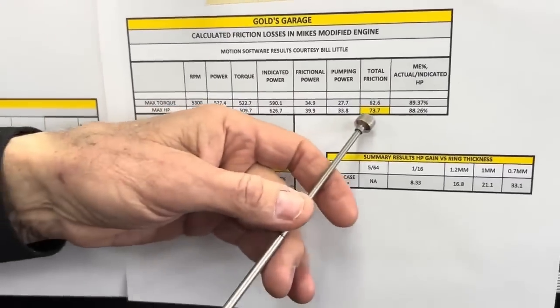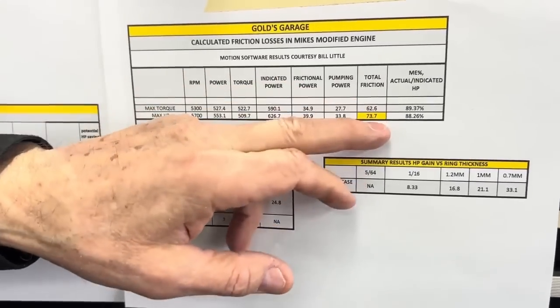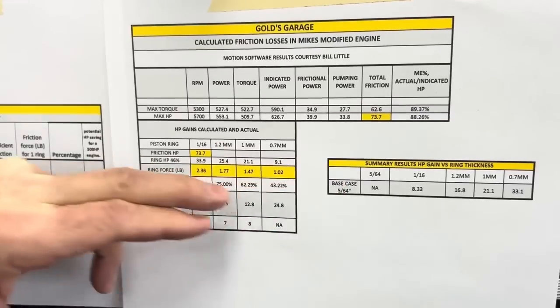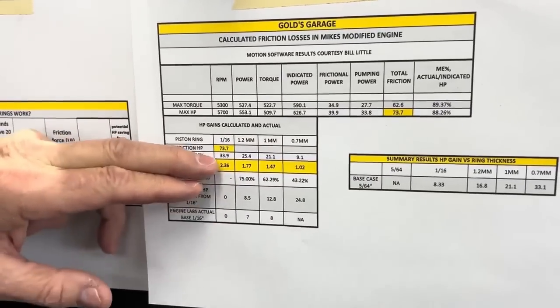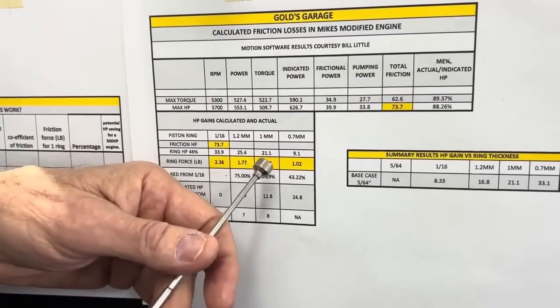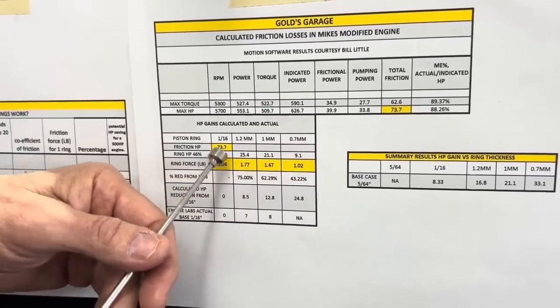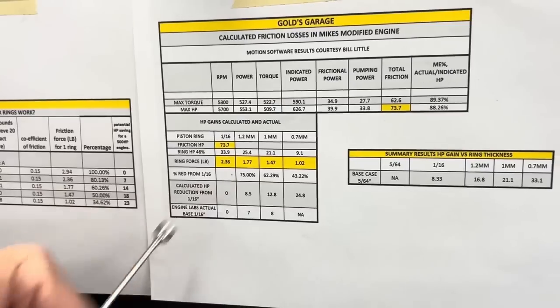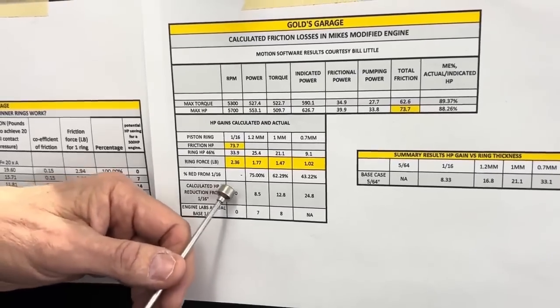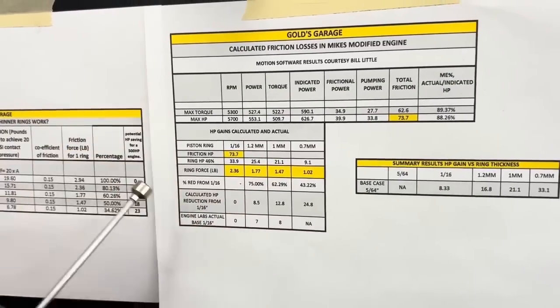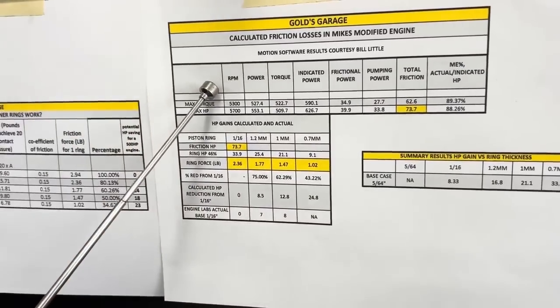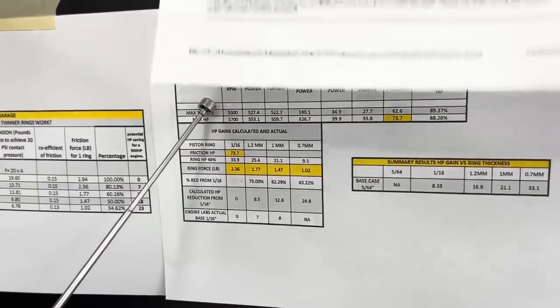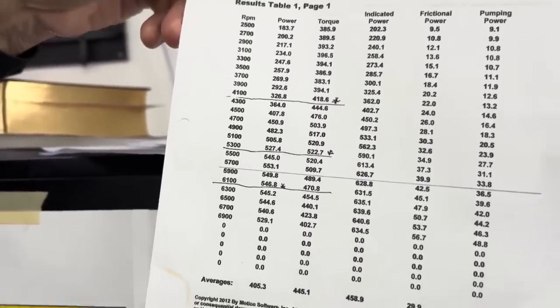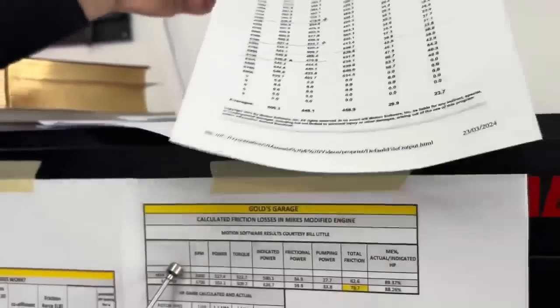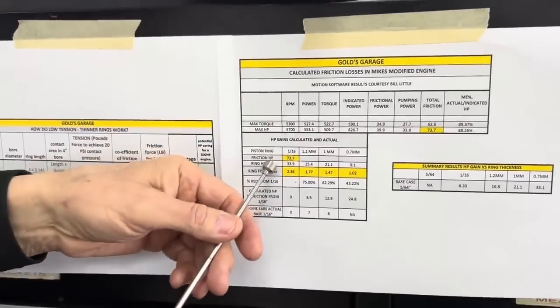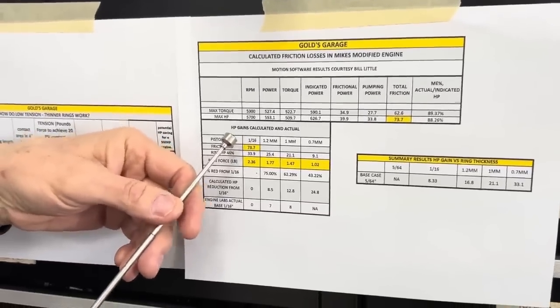The calculated friction horsepower is 73.7. So I take that 73.7, I bring it over here, and then I use the area of the piston ring to calculate how much horsepower gain I would get based on that. And it comes out to 8.5. The problem is, it's not a problem, but in the calculation that Bill did, Mike's engine has 1/16 rings. So I can't compare 1/16 to 5/64 because we're starting with a 1/16 ring. You have to remember that. But I calculated it backwards to do that.